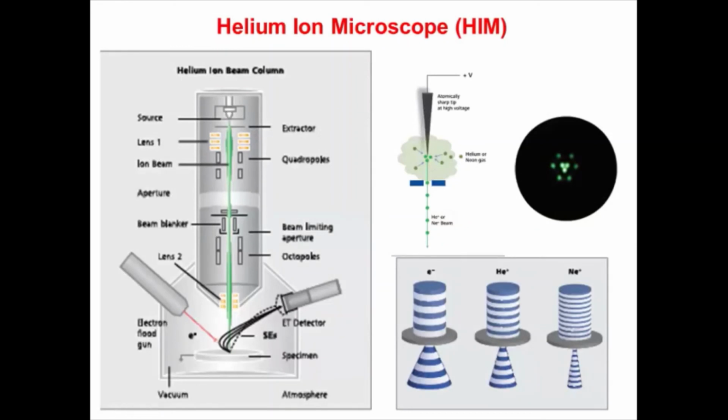Similar to field electron emission, there is field ionization. In field emission, we have the sample biased at a negative potential. But if the same sample, a very fine needle, is biased at a positive potential, and if I have some gas in the vicinity, and I pull this tip, then I can see the surface atoms of this tip on the screen.